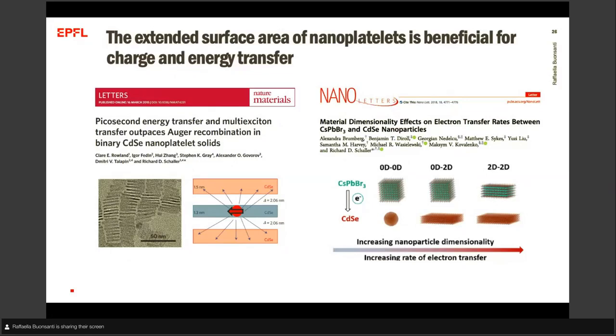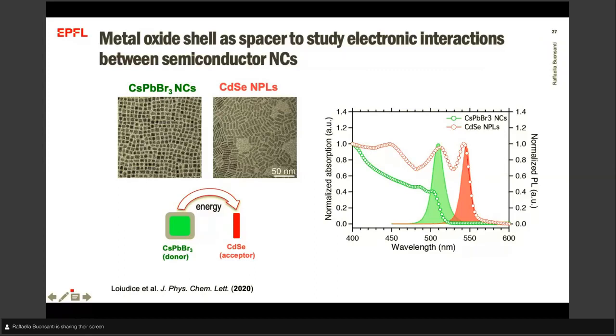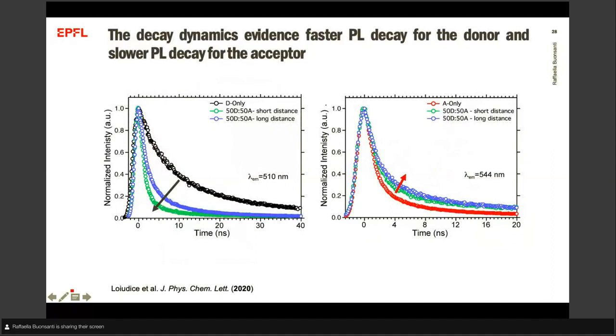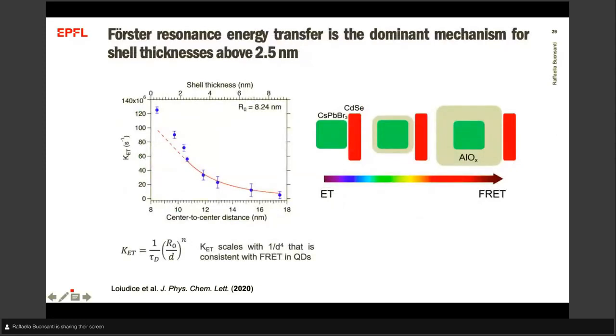And then we decided, so great introduction again, because these nanoplatelets were already mentioned. There were in the literature some interesting examples of how dimensionality impacts electron and energy transfer rates. And so we decided to explore energy transfer, to use the shell to build a platform to study the transfer of electronic energy from perovskite quantum dots to cadmium selenide nanoplatelets. We used different spectroscopy techniques, and what we observe is a faster PL decay for the donor and a slower PL decay for the acceptor. From this data, we extracted the average lifetime, and we could plot the energy transfer rate versus the distance between the quantum dots.